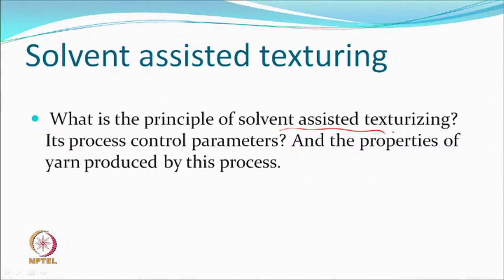If you do not work at high temperature, partial melting will not happen and recrystallization will not take place. So you need assistance. For a material like acetate or triacetate, using some solvent means that instead of going to a very high temperature, at half the temperature you can do the job, and at that lower temperature degradation will not take place.